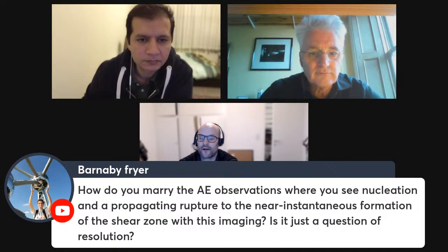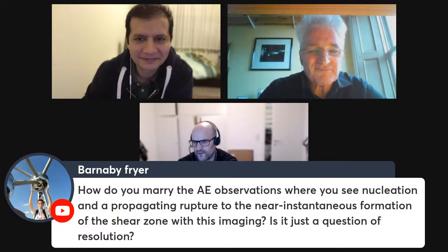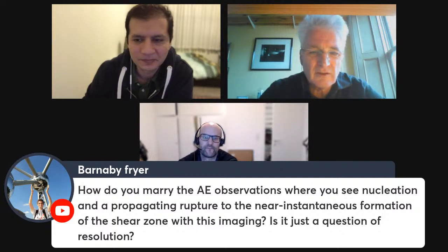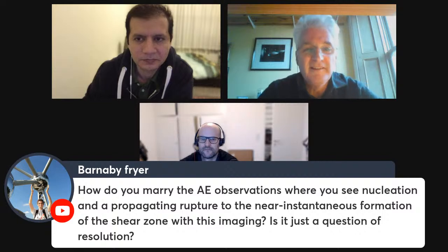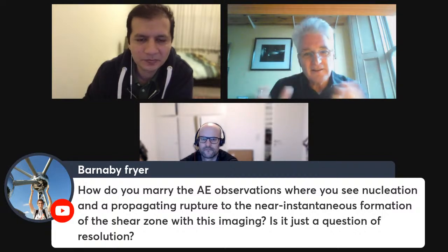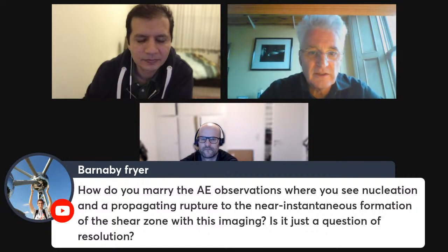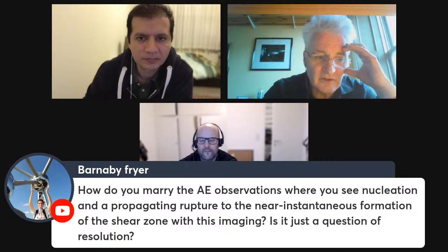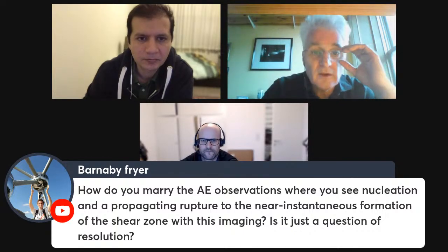Yeah, excellent. The next question is by Barnaby Fryer, asking, how do you marry the acoustic emission observations where you see nucleation and the propagation rupture to the near instantaneous formation of the shear zone with this imaging? Yeah, I think the acoustic emissions, especially when you've got the servo control and so on, and synchrotron is a noisy environment. So our magnitude threshold is pretty high. I'd be more comfortable if it was lower. But this is an optimization problem, and this is the optimal we could do to maintain the image resolution with acoustic monitoring. And as the X-ray sources get stronger, we'll be able to use bigger samples, and then maybe we'll have a better resolution of what's going on.